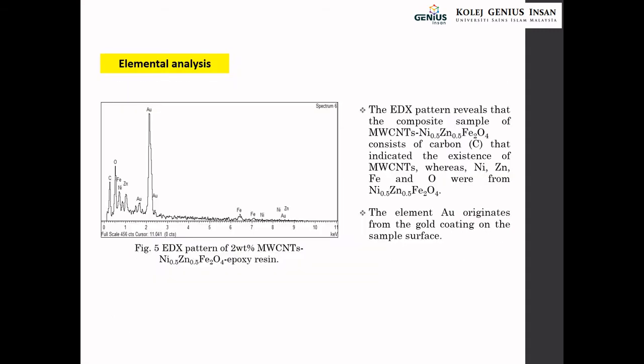For elemental analysis, this is the result of the EDX pattern. It reveals that there is C, which comes from the multi-wall carbon nanotubes, whereas nickel, zinc, ferrum, and oxygen were from nickel zinc ferrite, and the element aurum originates from the gold coating on the sample surface.